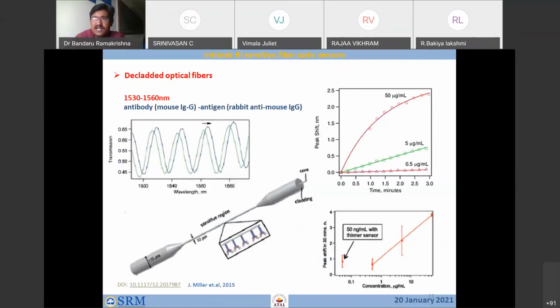In this case, people have tried the decladded fiber coated with antibodies, and another molecule, the antigen molecule, is given. So when the concentration is increasing, you see the binding kinetics change. However, here the light which is transported inside the fiber, for example at 1550, you see there is a peak. That peak is shifting towards the right side, towards the higher wavelength side, as the binding event is happening. When the molecule binds to the surface, the refractive index is changing, and because of this change in refractive index, this wavelength shift is observed. So here there is no absorption happening, it is simply a shift in wavelength.